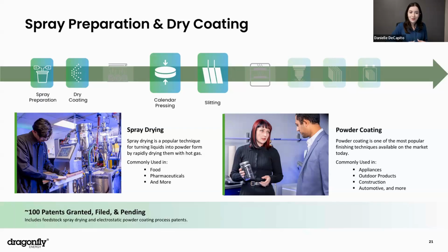So to tie it all together, Dragonfly Energy's proprietary dry electrode process offers clear advantages over the traditional manufacturing process. It's fully chemistry-agnostic. We see a reduction in its CO2 footprint. It requires less energy, and it requires much less space, lowering both upfront and long-term capital expenditures. A third-party evaluation conducted by Sphere Energy actually found that our patented process achieves over a 70% reduction in energy consumption compared to the traditional methods. By pioneering this technology, Dragonfly Energy continues to lead the industry towards a more efficient and sustainable production future.